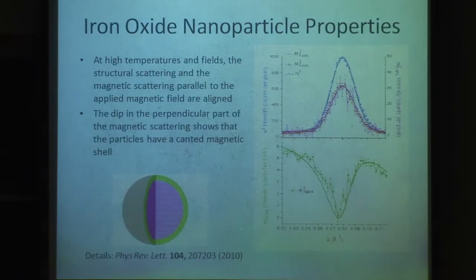Using those equations, we found some interesting results about our iron oxide nanoparticles. At high temperature and field, we found that both our structural scattering and our parallel magnetic scattering looked the same. They both had a nice peak right around about 0.8 Q, inverse angstroms. And that peak corresponds to a cluster of nanoparticles working together and working the same way. And even though those peaks have very different intensities, they have the same general behavior.